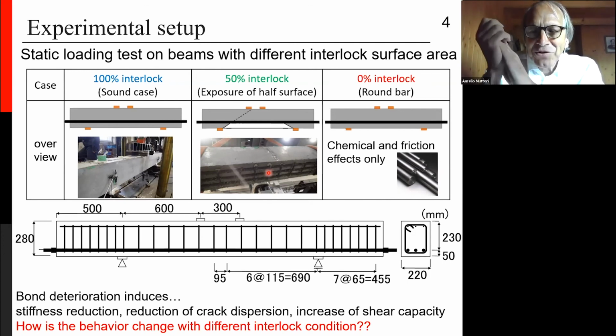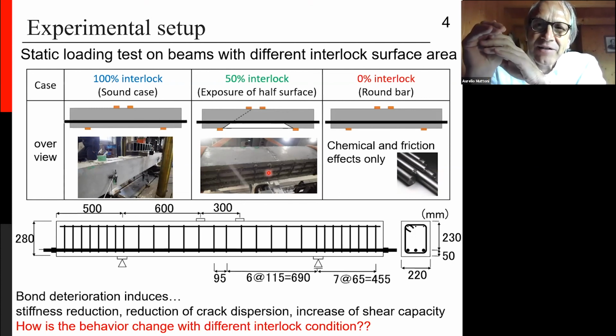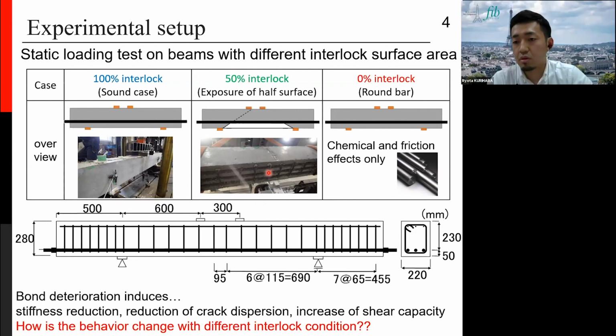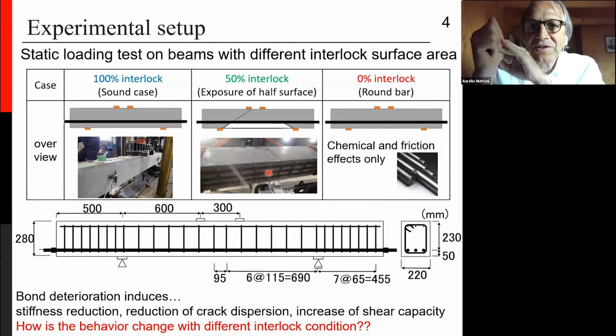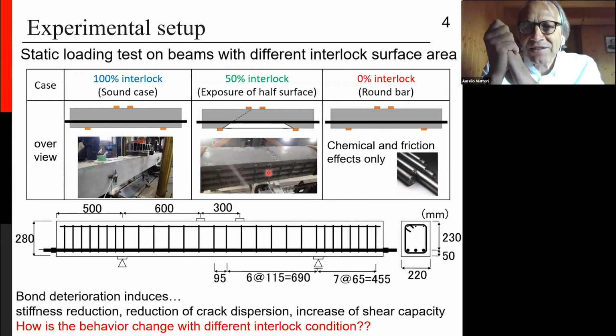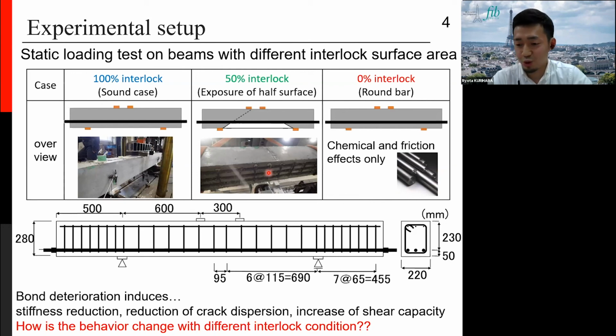I understand, but I was mentioning something different. If you have a longitudinal crack, then you will have reduced contact zones between lugs and concrete. And this phenomenon is very similar to what you wanted to investigate, which is the loss of lug height. Yes. So you could easily adapt the models which exist for longitudinal cracks to the case of loss of lugs, in my opinion. Thank you. In the final stage, I want to integrate the longitudinal corrosion cracks and the lug loss.